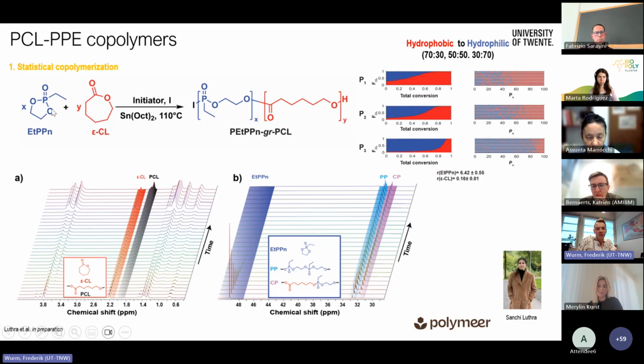So we just mix two monomers, add a catalyst, and then you get these copolymer structures. And she developed very nice NMR characteristics. Here we look in situ in the polymerization, so you do the polymerization in the spectrometer. And over time, you can follow how the monomers are incorporated and also which neighbor they have.